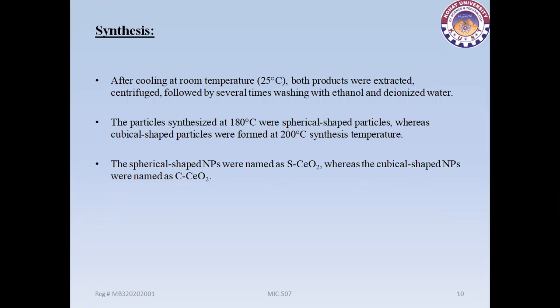So after cooling at room temperature, both products were extracted, centrifuged, followed by several times washing with ethanol and deionized water. The particles synthesized at 180 degrees were spherical shape particles, whereas cubical shape particles were formed at 200 degrees centigrade synthesis temperature. The spherical shaped nanoparticle were named as S cerium oxide, whereas the cubical shaped nanoparticle were named as C-cerium oxide.